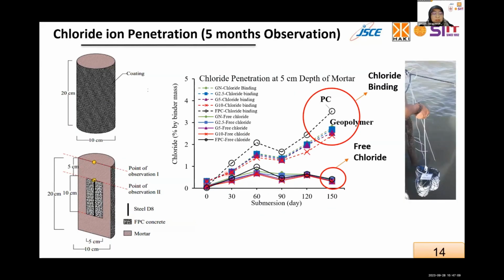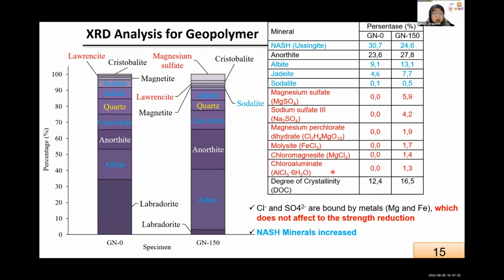And here at the 5 centimeter depth of mortar, the very inner cover, both geopolymer and Portland mortar showed chloride binding, where free chloride ions were found in both systems. Then, to understand the change of the minerals of geopolymer mortar, XRD analysis was conducted on specimens before and after immersion. This is before and this is after. After 5 months, the product of geopolymer increased, the blue one, alongside a notable enhancement in its capacity to absorb chloride and sulfate ions.